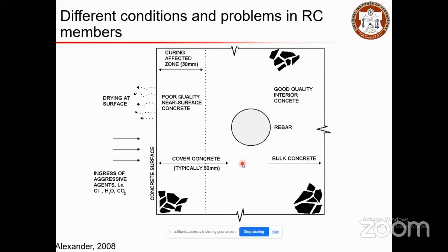Depending on the exposure, moderate or severe, you vary or increase the cover depth, because if you increase it too high, then it is not good for your concrete. Why? Your concrete is weak in tension and good in compression. So as you increase the depth, that concrete region may not withstand the tensile stress, and you may end up having a lot of spalling in the covercrete region itself. When the covercrete region spalls, that is going to expose your rebar to the outside environment, and then the aggressive agents would react and affect your rebar to induce durability issues.